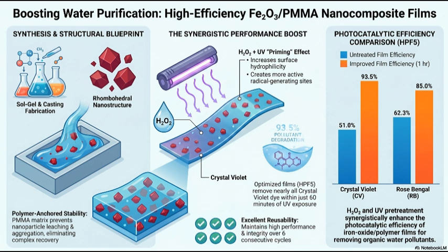The researchers tested its durability rigorously to prove its viability as a replacement for current tech. They took the treated HPF5 film, washed it, and reused it for 6 consecutive cycles. Even after 6 full battles against these highly toxic dyes, the composite showed excellent stability with only a microscopic drop in efficiency. The structural integrity of the PMMA held up perfectly, preventing any nanoparticles from leaching out into the water. That is the ultimate goal, a system that cleans the water and leaves absolutely zero secondary pollution behind. It's an incredible piece of materials science.